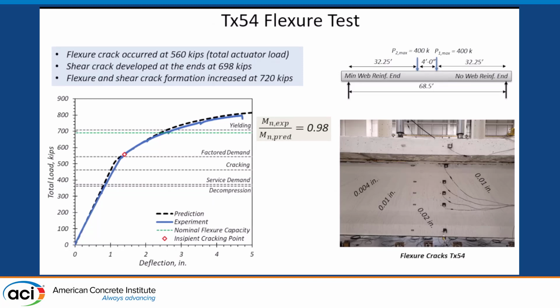So just a few highlights of the testing. We tested in flexure, which meant that we were loading here at the center of the girder. We have a chart here showing the total load, so that would be each actuator added together. So we're going up to about 800 kips total load. We have a black dash line, which is our predicted performance, and we have a blue solid line showing the experimental values that we're measuring. And the horizontal lines are showing decompression, service demand, cracking, and factored demand.